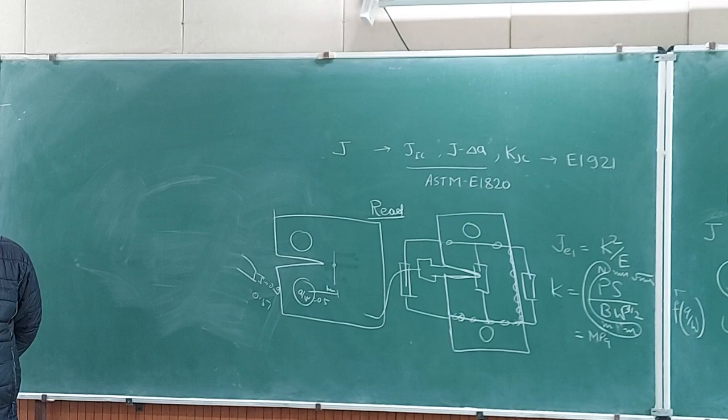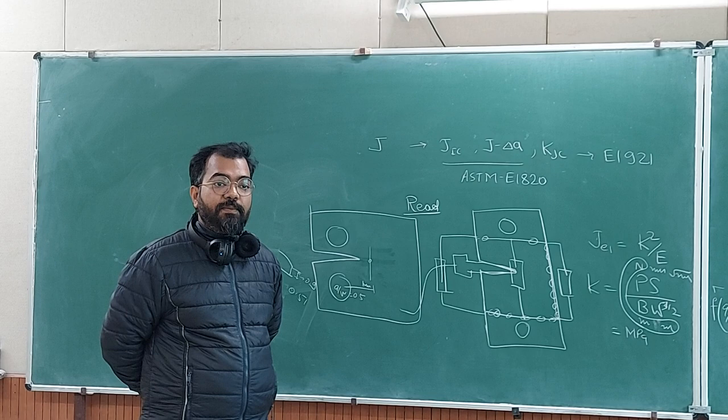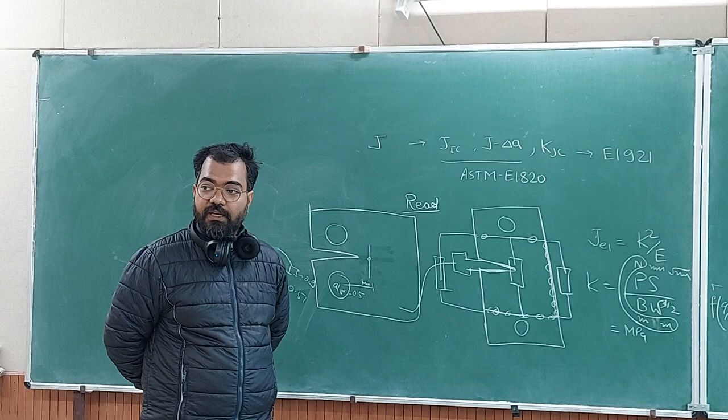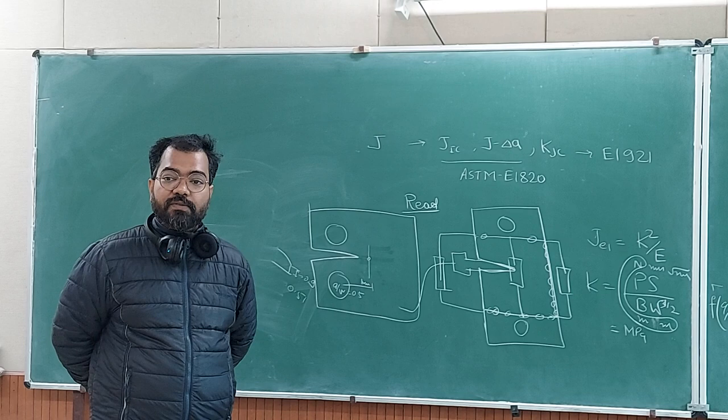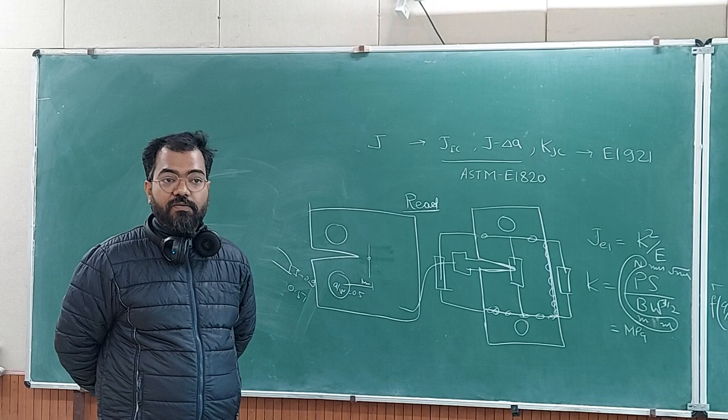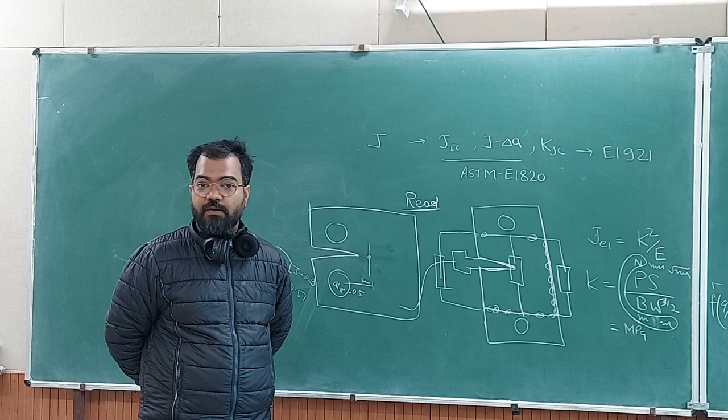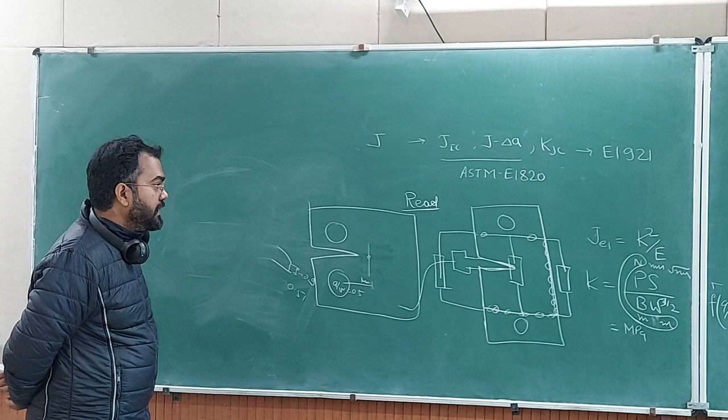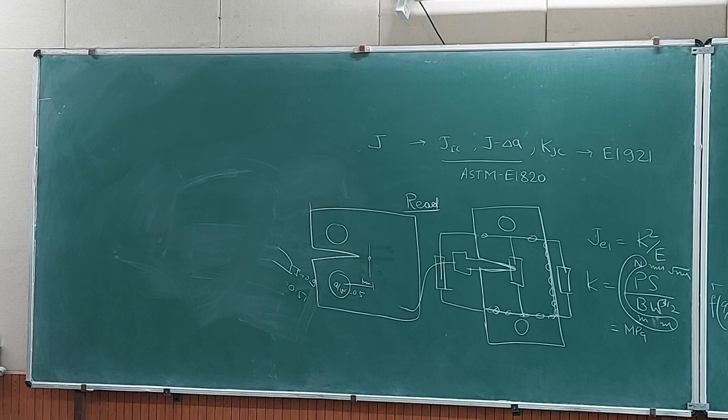So what is happening in these materials? These are ductile materials. In ductile materials, the crack is propagating stably. There is no catastrophic failure unless you load it to a very high value of displacement. Even then, some materials cannot fail that way. For example, a lot of steels we have today will not fail in a catastrophic manner at room temperature. We don't make brittle steels these days. So you are going to get a lot of stable, slow ductile crack growth.